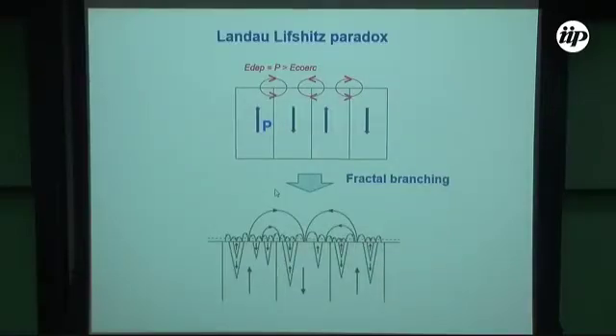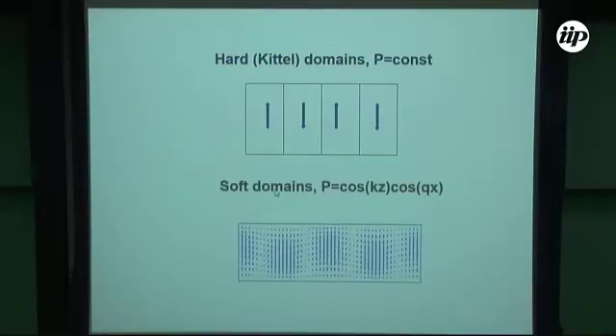But actually what we claim is that what we have now is another solution of the Landau-Lifshitz paradox, because in Landau-Lifshitz they make the assumption of constant, flat polarization, and in the case of Ginzburg-Landau, the polarization can change its modulus. So in principle, the charge is not only concentrated at the top, but it can penetrate also inside of the sample and gives another solution of the paradox. So no fractalization, just the softening of the polarization, the PZ component of polarization, in the wall.